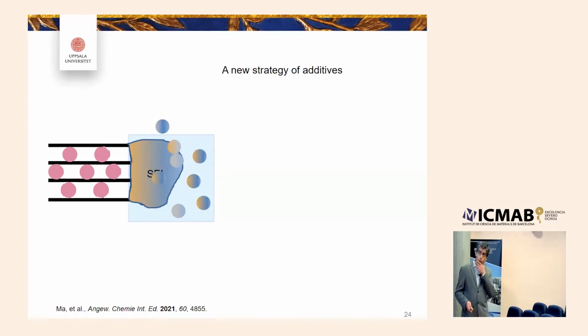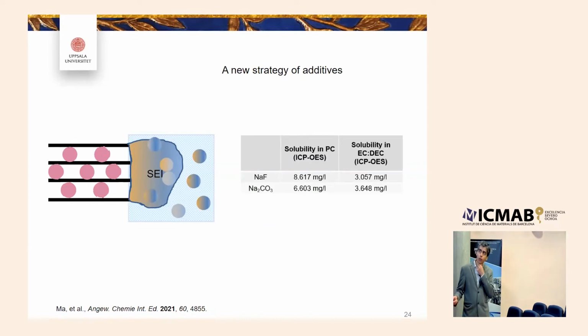That's what we tried to do. We looked at two different components, sodium fluoride and sodium carbonate, which have different solubility in PC and EC:DEC. There's a clear difference: they are much more soluble in PC compared to EC:DEC. So our expectation is that saturation of PC electrolyte by these species should have a much more visible or detectable influence compared to EC:DEC.